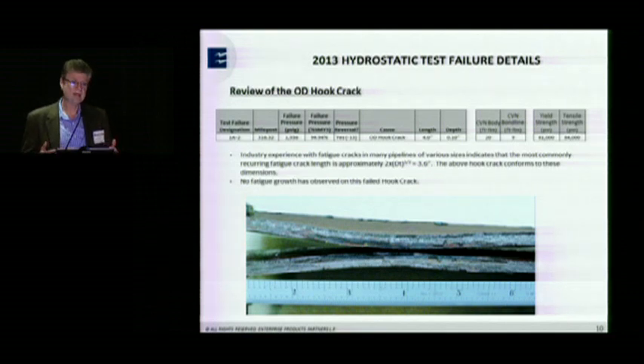When I went back and looked at the failures that occurred in 2013, a lot of them are hard to put into a failure assessment diagram. There were a couple that were an OD hook crack matched with an ID hook crack. I didn't want to get into that; it makes it a little bit difficult to model. And there was some stitch welding associated with hook cracks. So what I did is I said, let's look at one that was a pure OD hook crack, and it was measured 4 inches long, 100 mils, which is about 40% of the wall thickness.